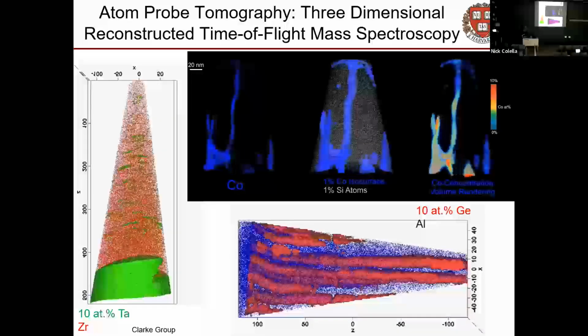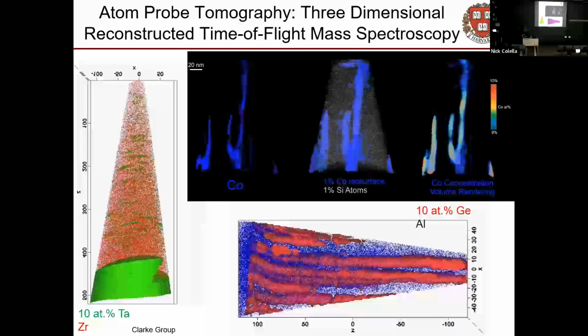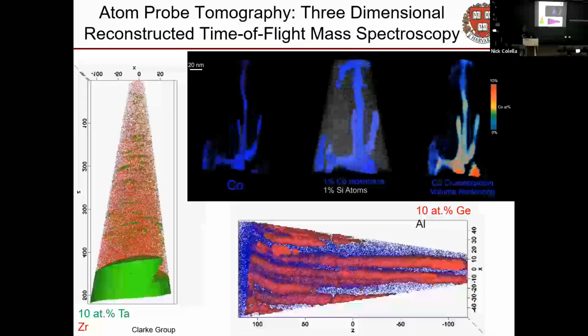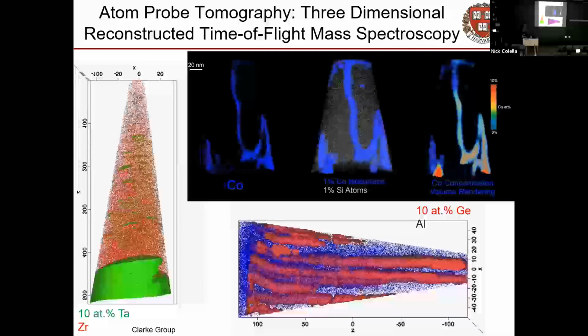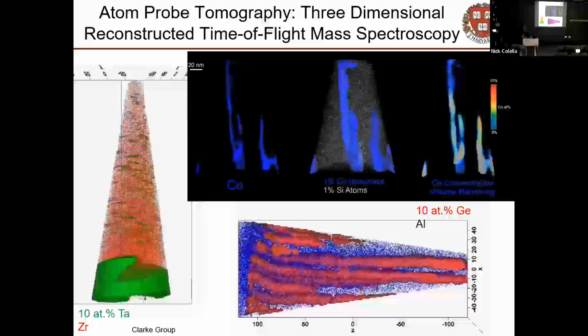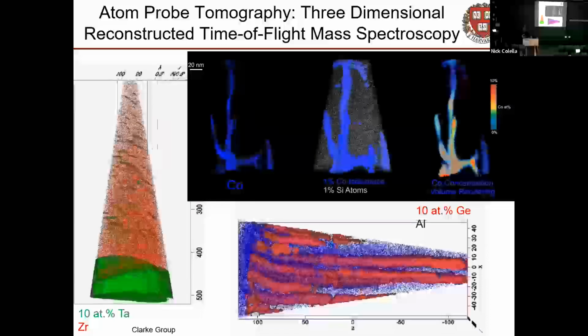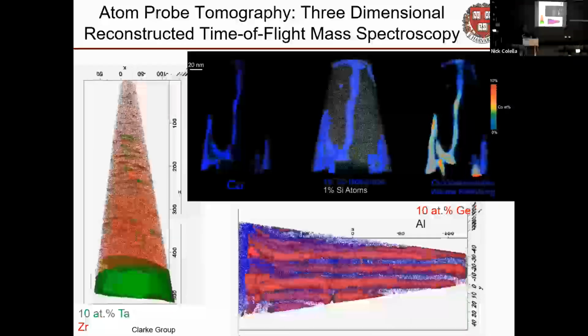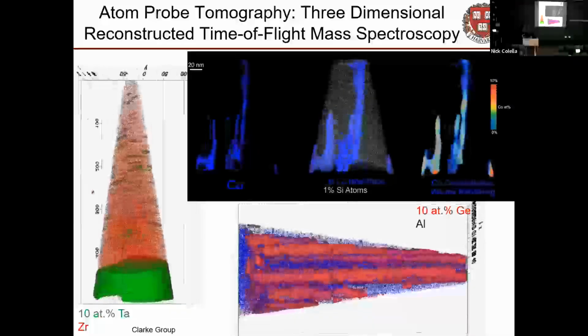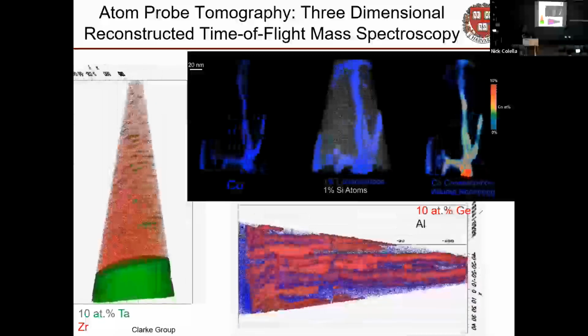But there you go. Every one of those little rotating gray dots is a silicon atom. The blue is cobalt. And we really are counting the suckers. And they're all where they ought to be. We got the same sort of thing going over here for a ceramic with tantalum and zirconium. We got a III-V with indium aluminum arsenide and germanium down there. This is fully 3D atom imaging.